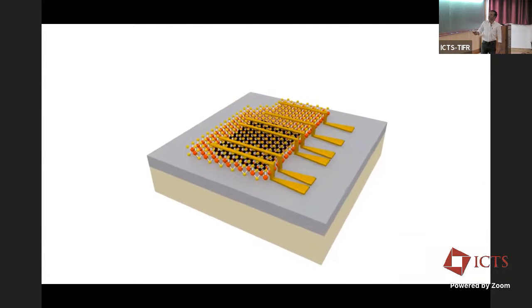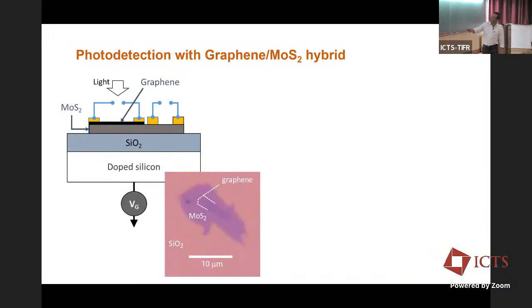Okay, and what we do is put electrical contacts such that we look at the electrical current through this when the whole system is illuminated with optics. This was the first experiment in which we looked at this hybrid structure in the presence of optical excitation. So this is how the schematic is. You can see the graphene and the molybdenum disulfide underneath, and electrical conduction through graphene is measured when the system is illuminated by some optical radiation.